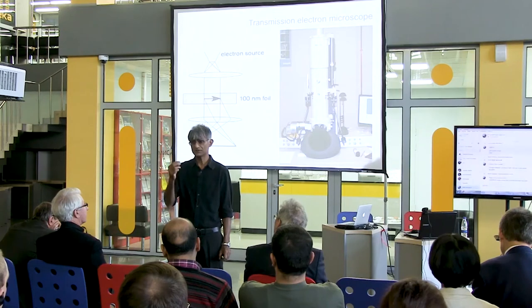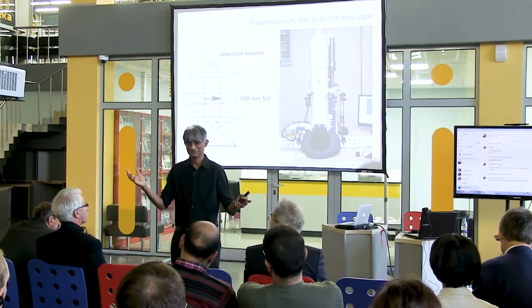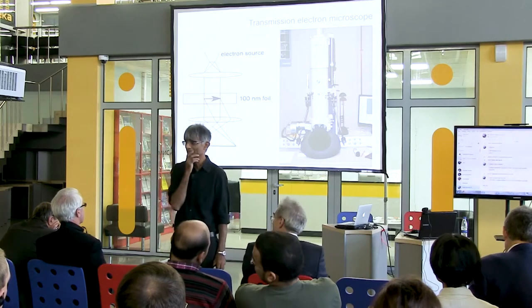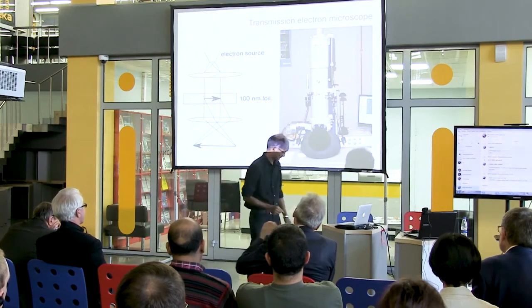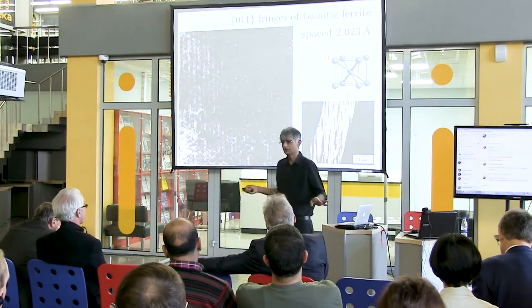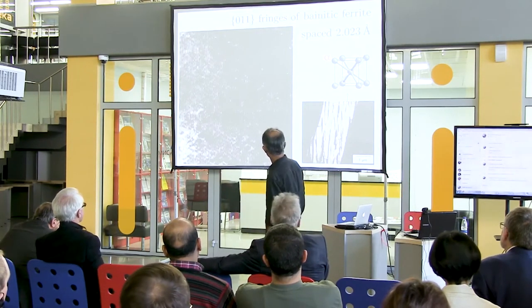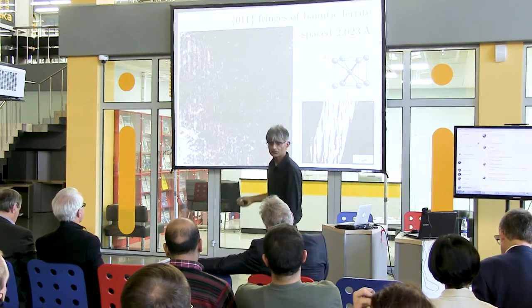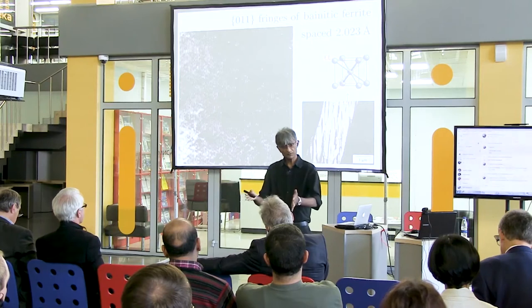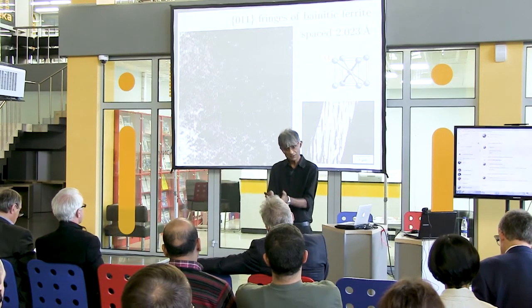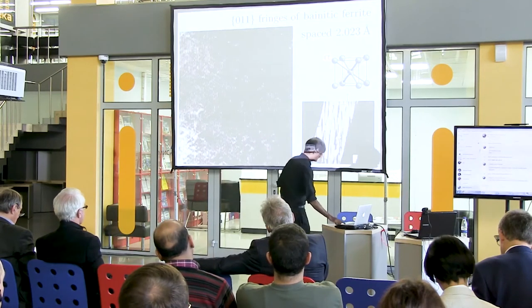Audience suggests 100 grams. Let us do a calculation. First, I'll show you how we measure carbon concentration using a transmission microscope. This is a higher resolution image of ferrite. You see these lines — those are planes of atoms — and in this case they are 011 planes. The presence of carbon will expand the distance between those planes. By measuring the interplanar spacing, we can work out the local carbon concentration. You can do exactly the same in the case of austenite — those are the 111 planes of austenite. In a high resolution microscope, dislocations and other defects also give rise to local strain fields, so you have to be careful when interpreting these images.